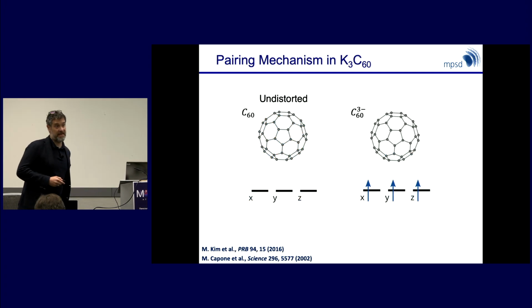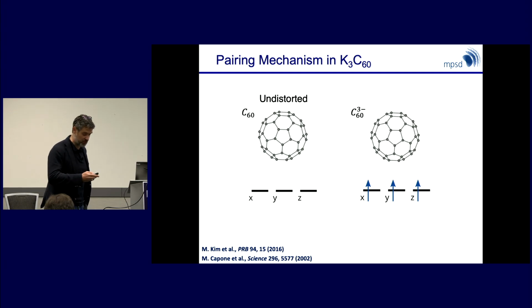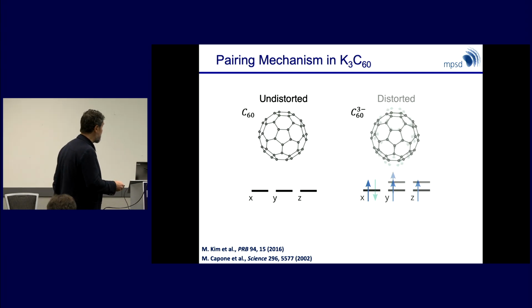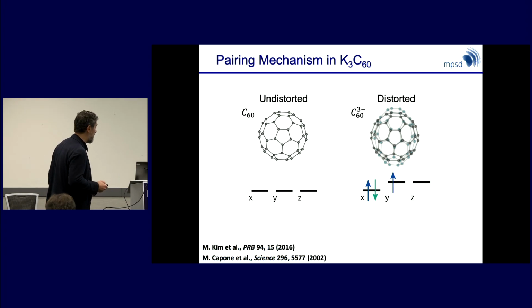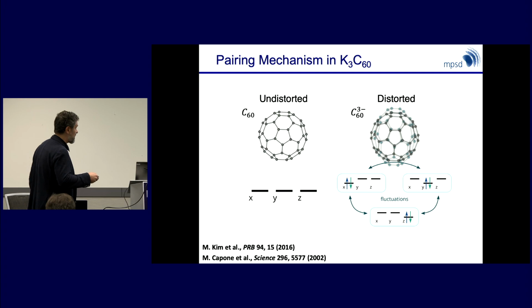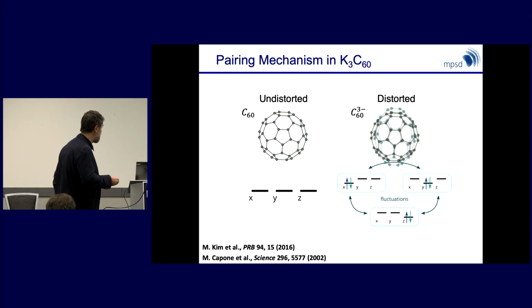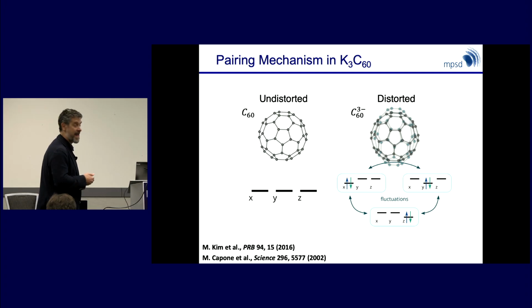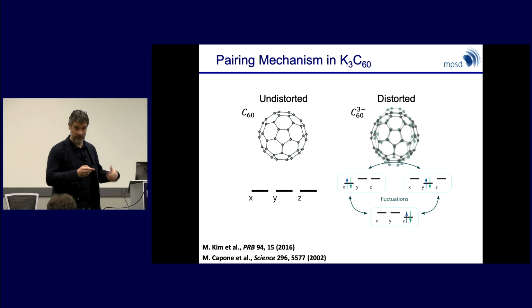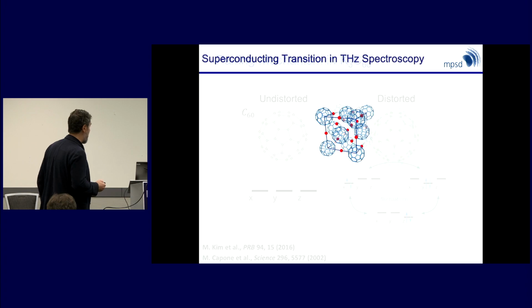The idea of the physics of the superconducting transition is that when you take the 3 times doped fullerene, you put 3 electrons in the lowest unoccupied molecular orbitals of the undoped C60, which readily form a low spin state because of Jahn-Teller distortion. So there's a dynamical Jahn-Teller distortion, an effect of correlations, and this promotes fluctuations in the different ways in which the singlet can occupy the various orbitals. According to these studies, the interaction between the dynamical Jahn-Teller distortion and correlations gives rise to the superconductivity phenomenon.